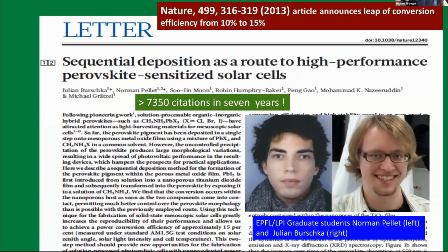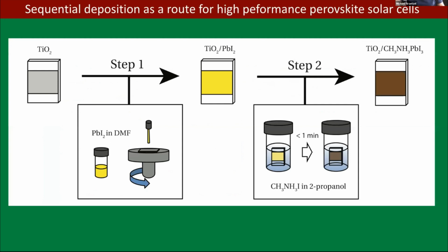And so, going back to how these films are produced, well, there's the sequential route, which we published first. You first put the lead iodide, and then you convert it to perovskite with whatever iodide, cesium iodide, methylammonium iodide. So it's separating the two phases for the perovskite formation. But a lot of people use just a single step, and this was our sequential deposition. First put the lead iodide down, then we expose it to, for example, methylammonium iodide and propanol, and that gave you the perovskite. It wasn't necessary to heat it; it formed immediately the black film.